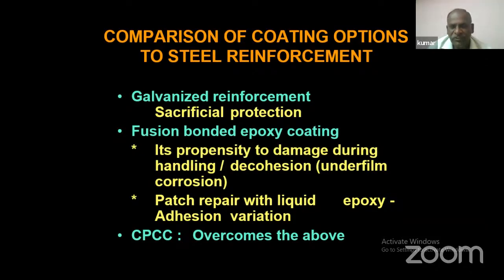Then which is best? We have to go for a cement-based system, if you are going for the inorganic type. The cement-based system is quite good for increasing the bond. But at the same time, all cement-based systems are brittle. So you cannot bend it. You have to do all the bending work first, then apply it, and then embed it inside. During handling also, there are chances of peeling off. For that, the cement polymer composite coating system, which is both organic and inorganic blended together, has been developed.